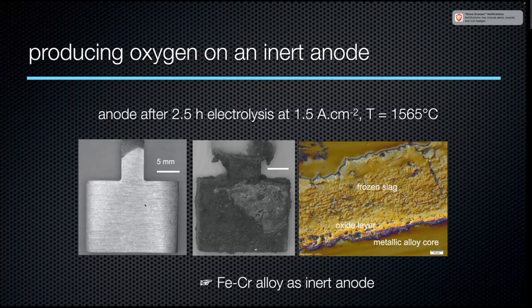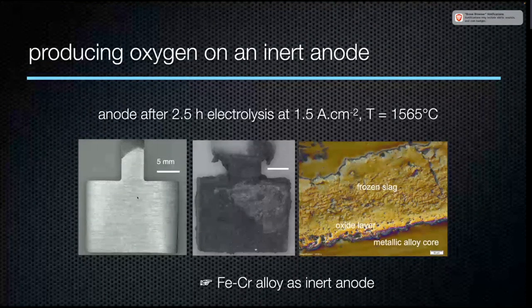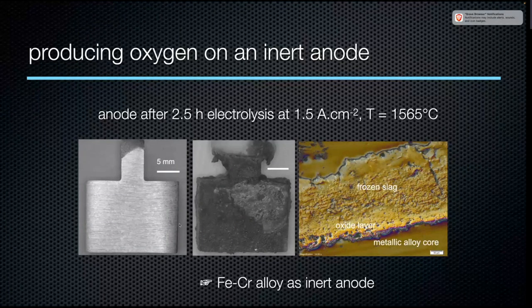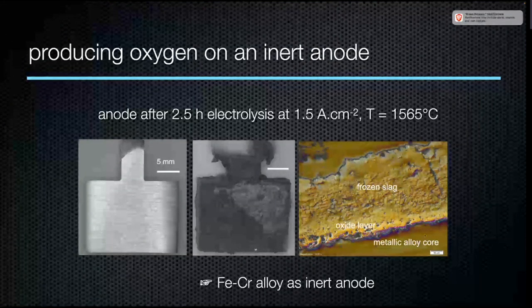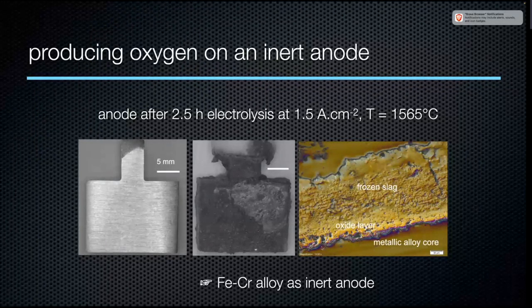And this is the alloy as received. And this is after operation for about 2.5 hours at 1565 degrees C. And you can see that this is still preserved. It looks ugly because this is the frozen electrolyte, but underneath it still looks like this. And this is the metallography of this. So this is the metallic alloy core, the iron chromium. And on the surface, we're making a chromate surface oxide layer.